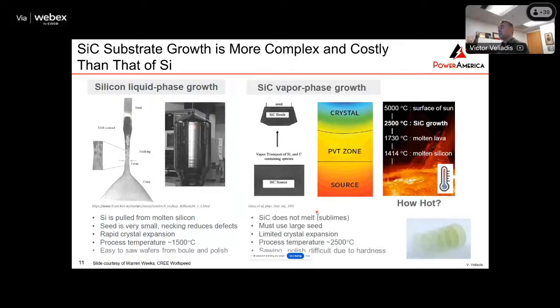This is not the case with silicon carbide. Silicon carbide melts at very high temperatures, so what you need to do is go to 2300 to 2500. The material will not melt, it will sublime. You need a seed crystal to start the growth, and the quality of your wafers, the quality of the boule that you're going to create is dependent on the quality of the seed layer. So it's a much more complicated process, and you also have to saw and polish silicon carbide, the boule, which is very, very difficult because of the hardness of the material. So more labor intensive, higher temperatures, and smaller boules means higher price for the wafers.